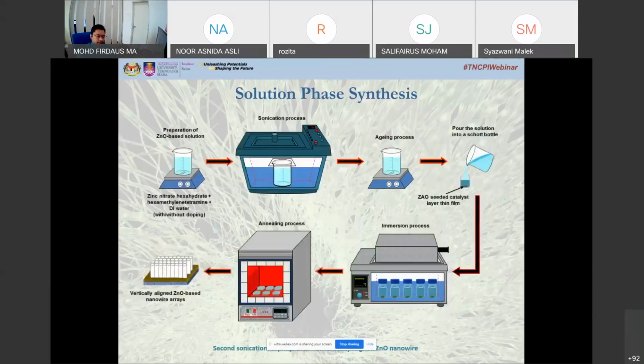And then for the development of zinc oxide wires, the same zinc base solution was used. Also, we introduce the sonication process to speed up the homogeneity of the solution, and we pour it into a vessel, a Schott bottle, and then we put it in a water bath for the evaporation process. And then here is the process to grow the nanowire, and then we go for the annealing process to make it a crystalline structure.